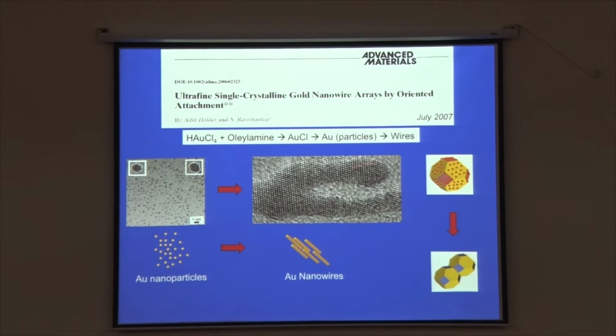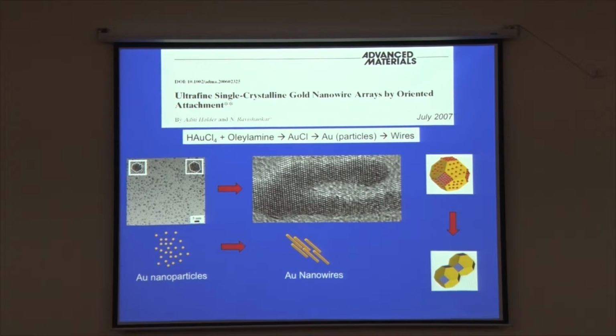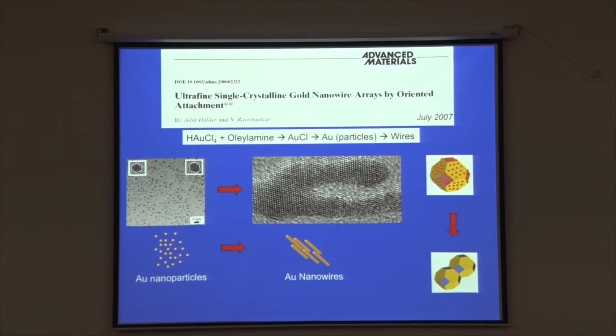As I told you, we start off by making gold nanoparticles. In this case, this is the shape that it adopts, as I told you, and it is bound by the amine, which is a surfactant in this particular case. It turns out that the amine binds very differently to the square facets, as I have shown here, and the hexagonal facets, which means that I can selectively remove the binding from the hexagonal facet. And when that happens, to minimize the surface energy, two particles would like to come and attach in this particular fashion.